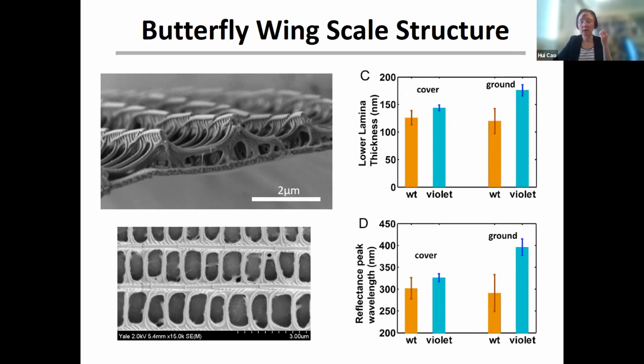So that means for this kind of structure color, in order to get it evolved, what we need to do is just change the feature size a little bit. By changing the feature size a little bit, the color will change. And this is much easier to do compared to pigment color, which I mentioned earlier.